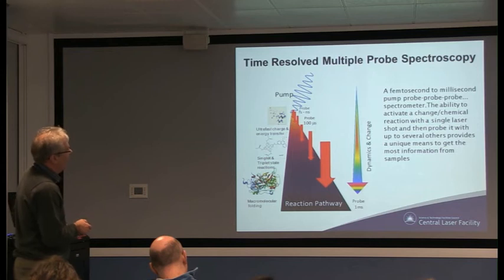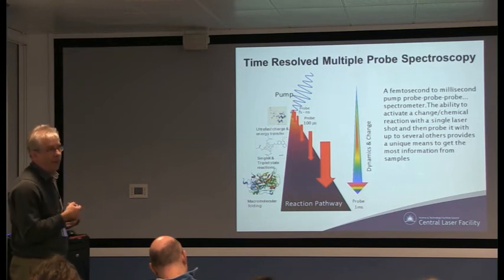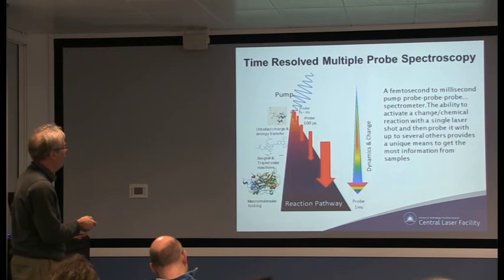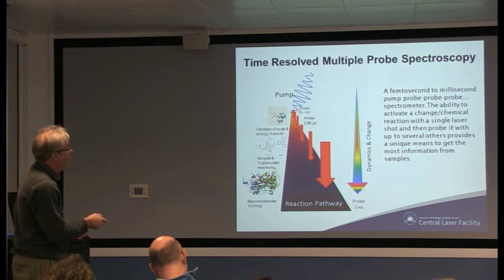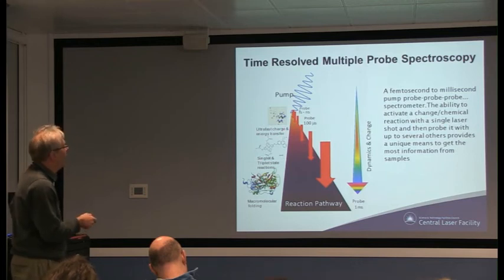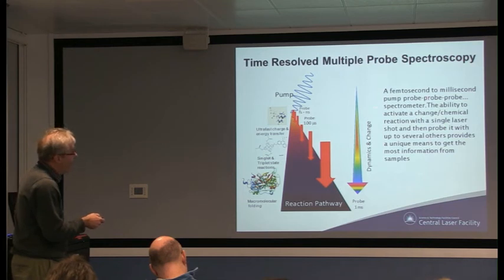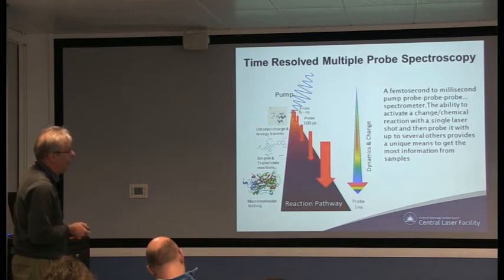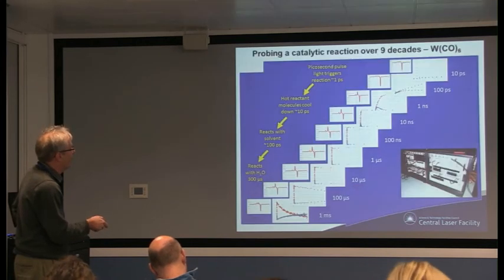So this time-resolved multiple probe spectroscopy is an example of one of the techniques. So I'll run through it so you get a sort of feeling for what's going on. It takes a pump laser source here to excite a molecule. Then the molecule will evolve, charge transfer, energy transfer, singlet, triplet states, folding techniques, whatever it may be. We then probe that state of the molecule at time scales after that, from femtoseconds, nanoseconds, microseconds up to milliseconds. So basically you're looking at the evolution of that molecule with time over, I think it's 9 decades of the time scale.